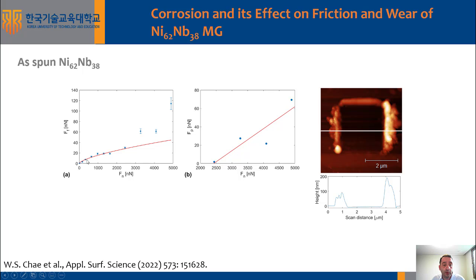Note the tip here was a polycrystalline diamond coated tip, and after scratching we observe a significant amount of pileups that speaks for real abrasion.